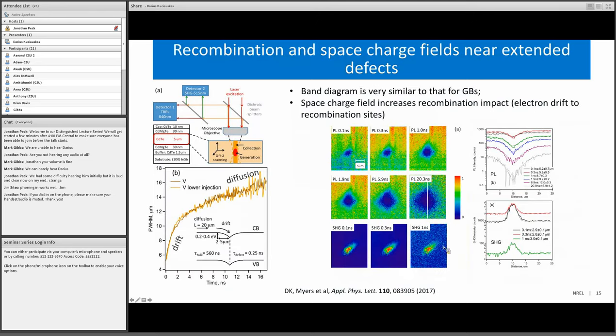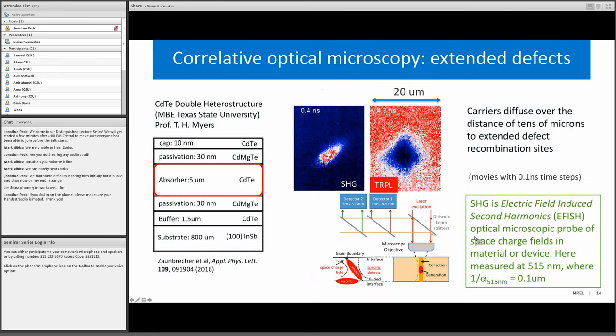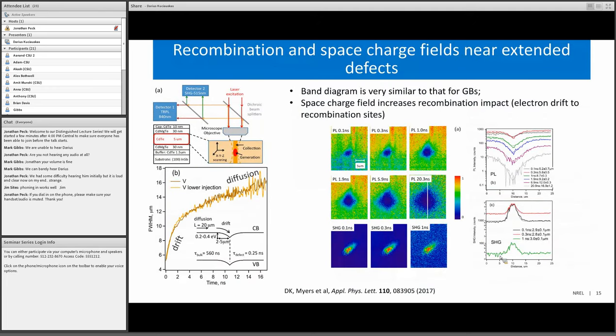The image on the left is showing the correlative second harmonic image in this sample, which is the optical map of the space charge field in this sample. The stacking faults are charged. They are surrounded by the depletion region, the space charge field. When we apply image analysis to that movie data in the previous slide, we see that there are two phases in this recombination: the fast phase, which occurs due to drift, and the slower phase, which occurs due to diffusion.